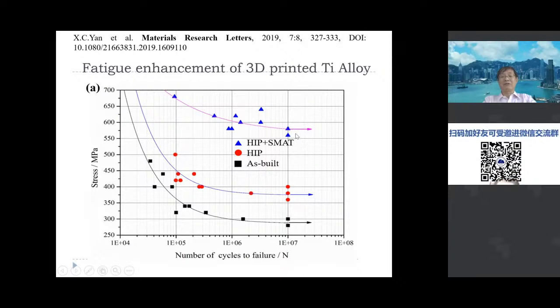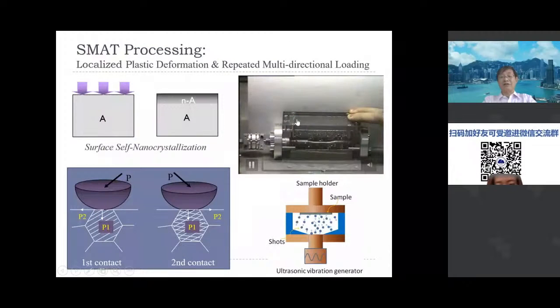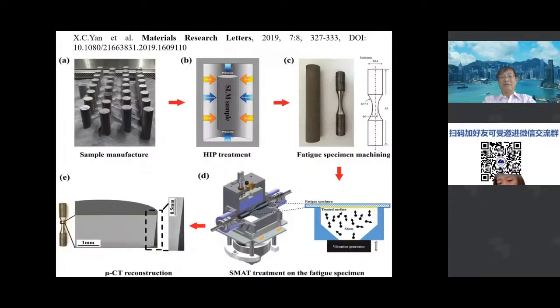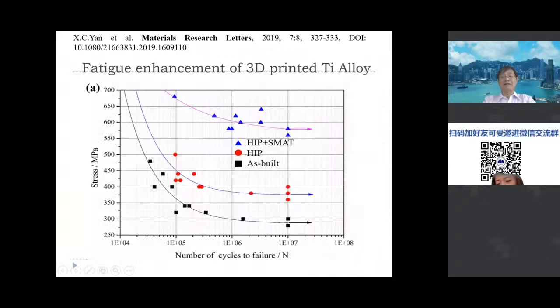So that is a very important achievement because, as you may see here, the surface mechanical treatment is a very convenient technology to treat complex geometry material, okay? Because the balls are in movement using the acoustic wave. So it can go anywhere in a complex geometry structure. Okay. Then we demonstrate that in the 3D printing of titanium, we can drastically enhance the fatigue strength.